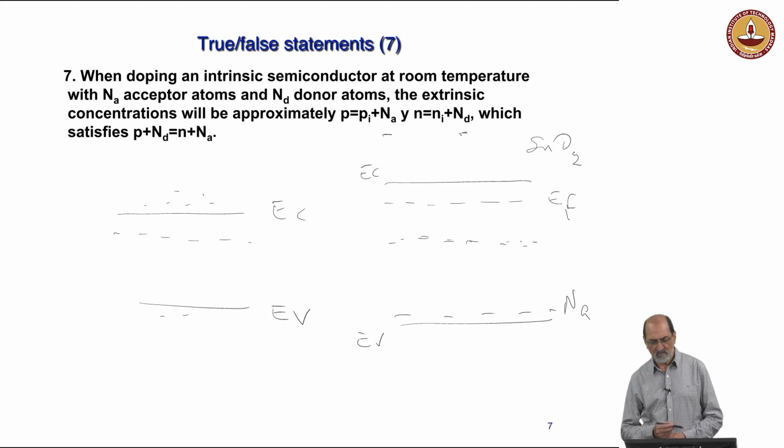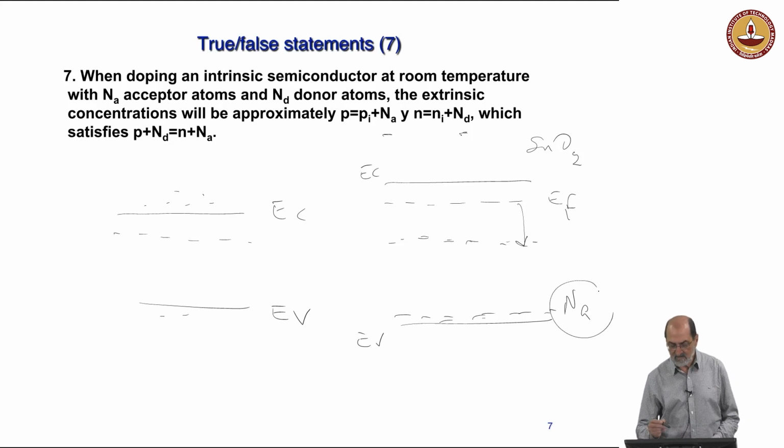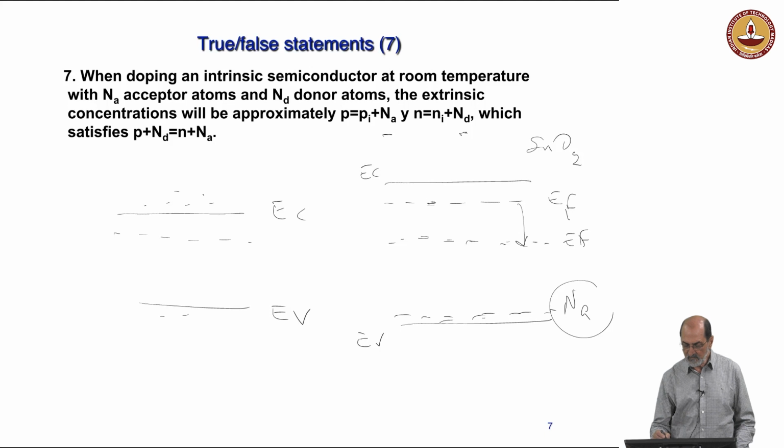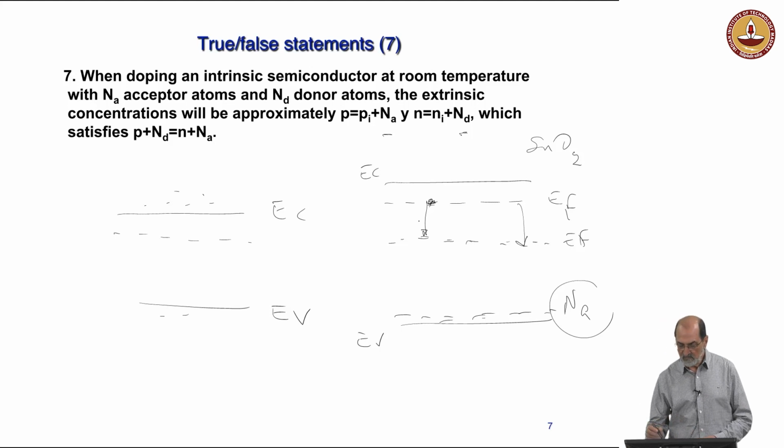Why doesn't it work? Because as the Fermi level goes down, the formation energy for oxygen vacancies decreases. So it's very difficult to do, and the vacancies are going to compensate the doping due to the acceptor levels. The reason is that once the Fermi level is low, when we create a state here, the electron which was here is energetically above with respect to the Fermi level. This would be the donor, from the donor to here.